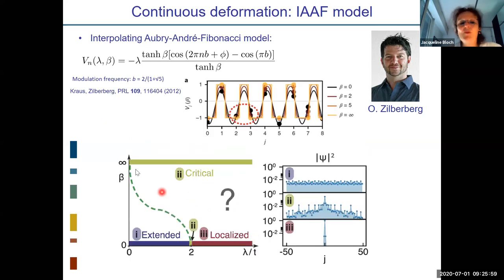So it means that you can draw a phase diagram like this, where lambda over T is the height of the potential, and beta is this parameter. For beta equals zero, we are in the Aubry-André regime, and we know that for small values of lambda we have extended states, and for large values of lambda we have localized states. And for beta equal infinity, we have critical states. So the question that we ask ourselves, with our theoretical friends from ETH and the group of Oded Zilberberg, is: how do the states evolve from extended to critical, from localized to critical? How do these localization properties evolve to continuously go from this quasicrystal to the other one?